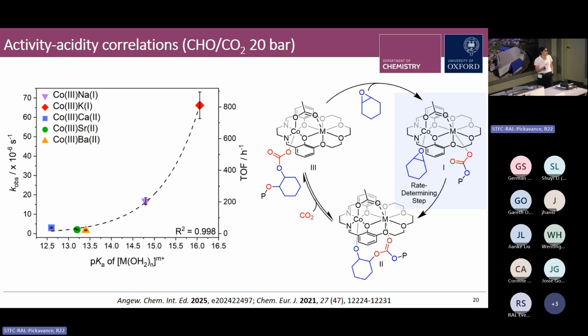We also tentatively propose that the non-linear nature of the trend arises due to the fact that the carbonate nucleophile can bind to the S-block metal via multiple coordination modes. So it can bind via a monodentate or a bidentate coordination mode, and potentially that gives rise to a reinforcing effect with changing S-block metal Lewis acidity and could give rise to non-linearity in the correlation.